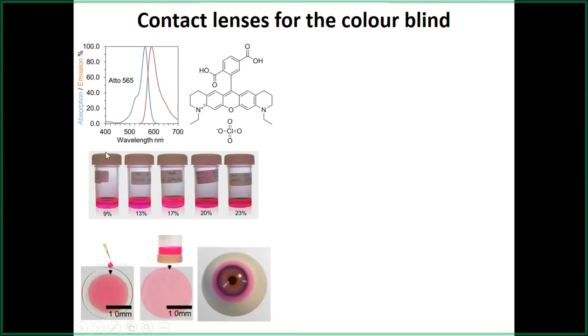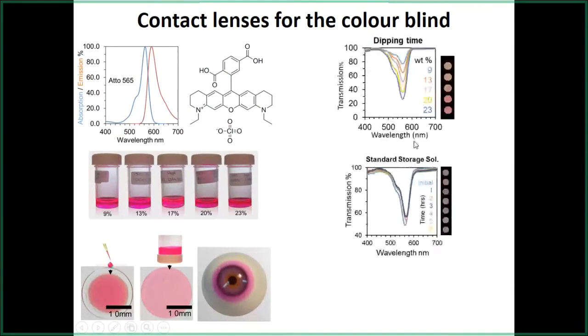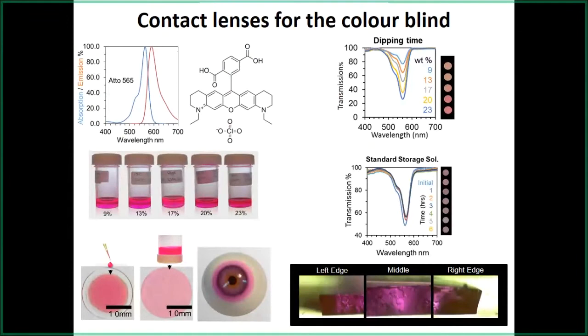Our initial approach was to use a commercial contact lens and dope it with this dye in different concentrations, and then we optimized the time for which you need to dip it into these concentrations. We also looked at whether, once the contact lens gets doped, the dye leaks. There was a bit of leakage, but at that time we didn't have a solution for it. For our contact lens, the dye distribution inside the lens was very uniform.